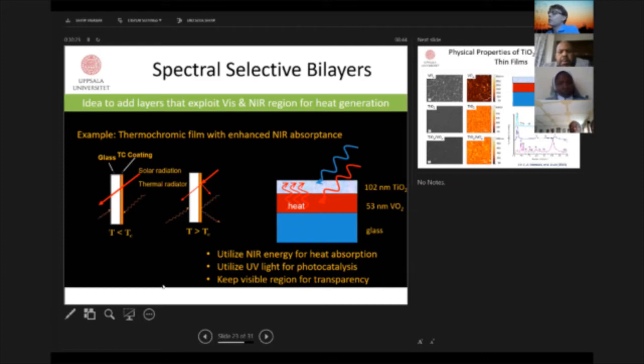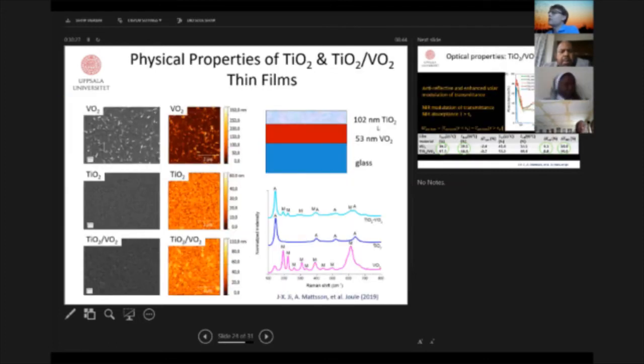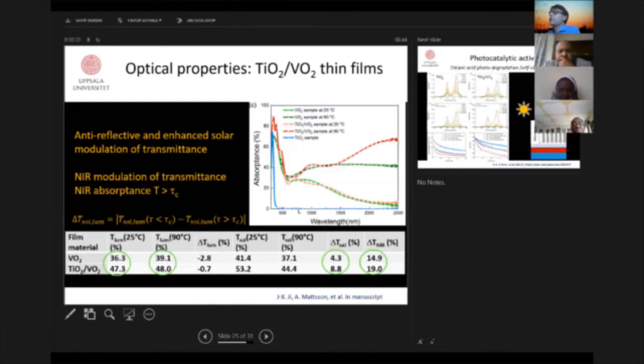So this concept, where we had a thermochromic film as a heat absorber and titanium dioxide on top of this, was realized by placing titanium dioxide on vanadium dioxide. These are just electron microscopy images, AFM and XRD images, proving the structure. And these are the optical properties showing that in the hot state, the absorbance of near-infrared light is higher on the vanadium dioxide film. This is a busy slide, but just believe in the numbers here, that they are absorbing more heat into this VO2 covered film, these guys here.